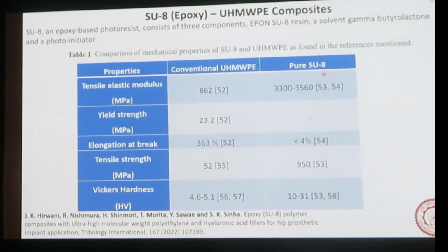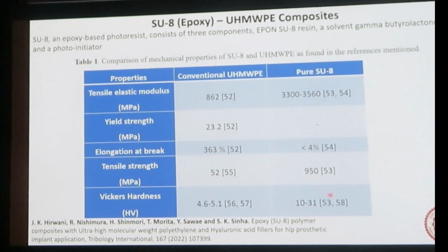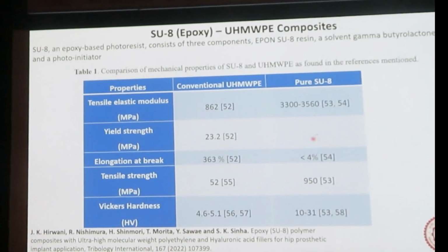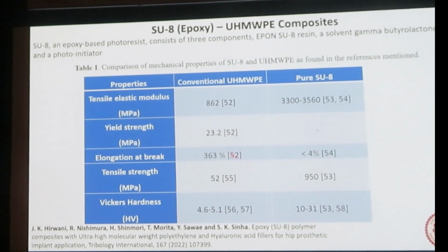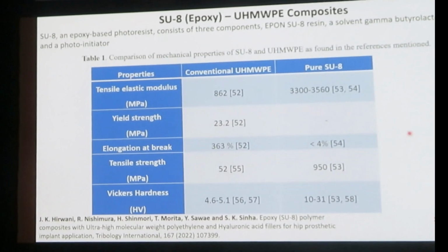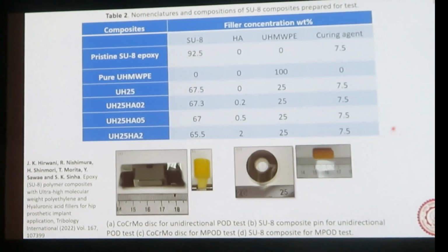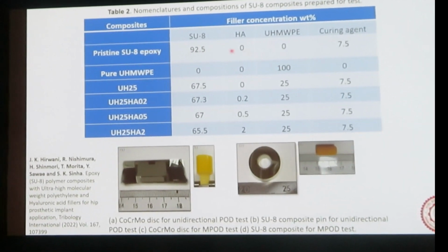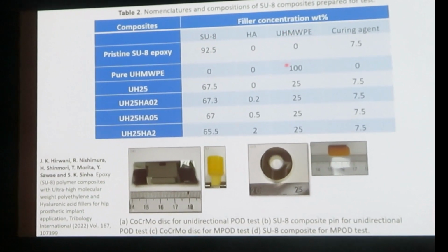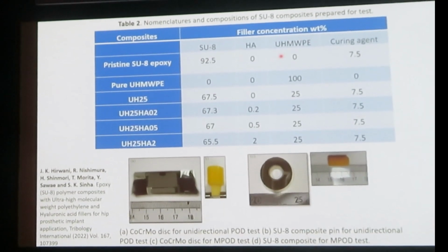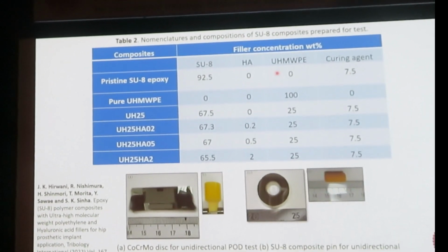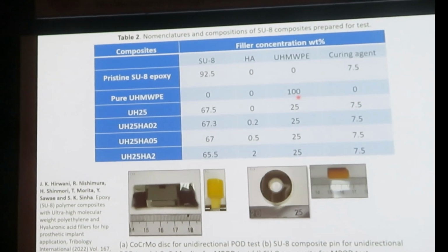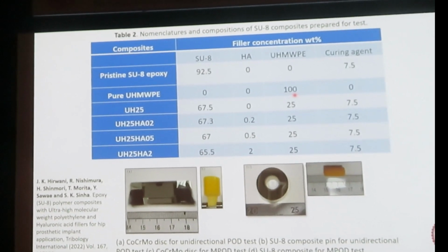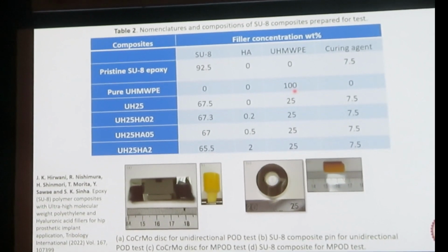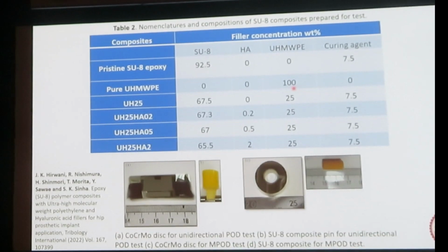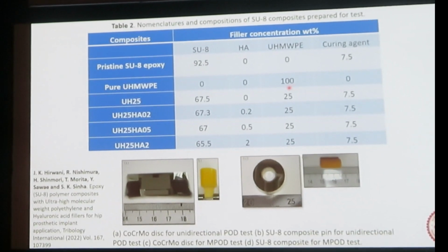Here we can see that pure SU8, which is basically epoxy, has better mechanical strength compared to UHMWPE. And the samples that we have made are SU8 with UHMWPE as partial filler. We used UHMWPE particles as fillers, and the idea was that epoxy is obviously not a very good tribological material, so adding a little bit of UHMWPE can help to improve the tribology.